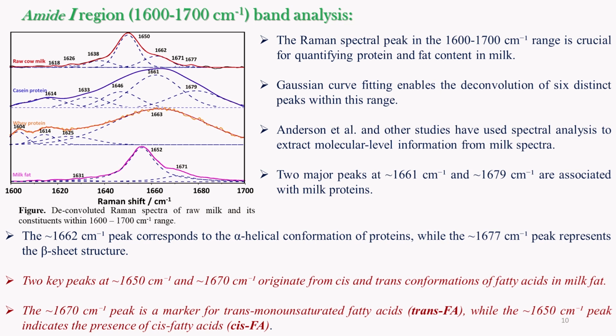So that's why it is written that the 1670 peak is a marker for the trans conformation. This one is for the trans, and 1650 is for the cis. So now we have a Raman marker band for this very informative information: if we measure 1650 and 1670, then we can know the ratio of these two species in your milk. So it is a kind of estimation of the cis fatty acid and trans fatty acid in your milk.